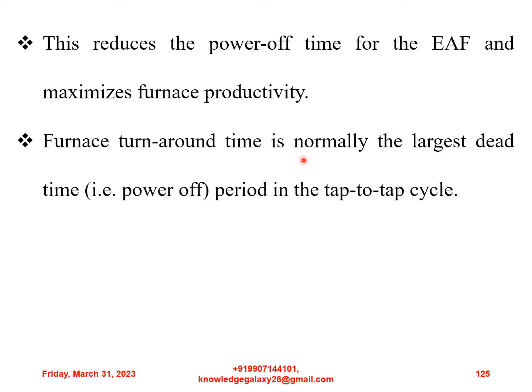Furnace turnaround time is normally the largest dead time, that is power-off time period, in the tap to tap cycle. So we must always try to keep the furnace turnaround time as low as possible. With advances in furnace practices, this has been reduced from 20 minutes to less than 5 minutes in some newer installations.